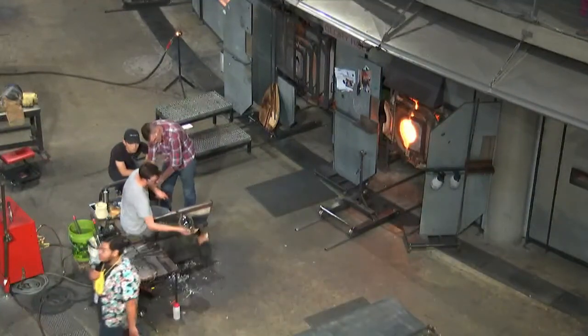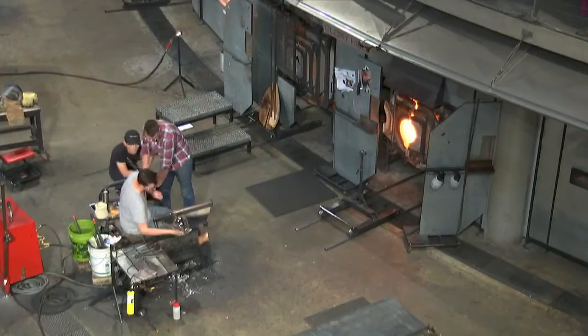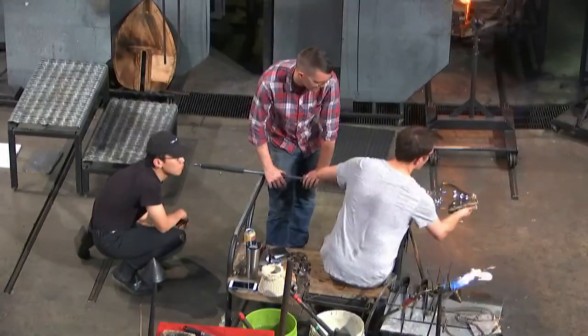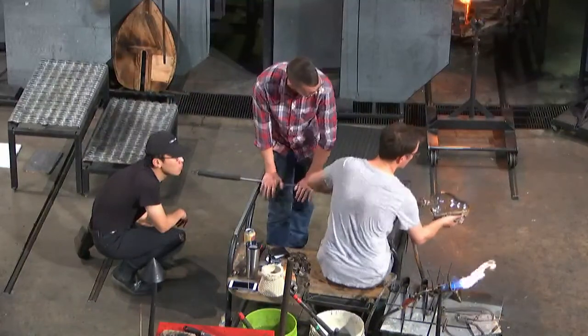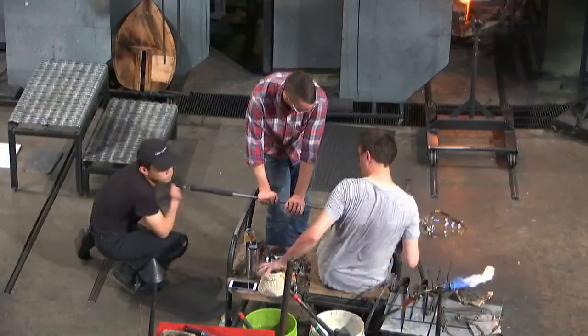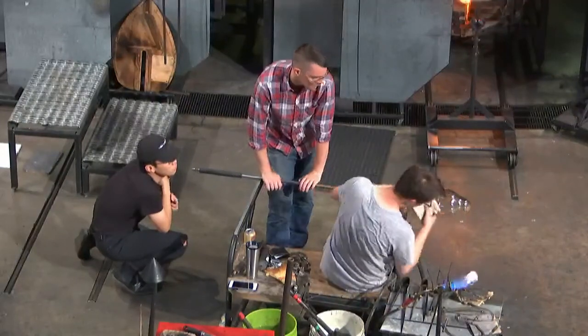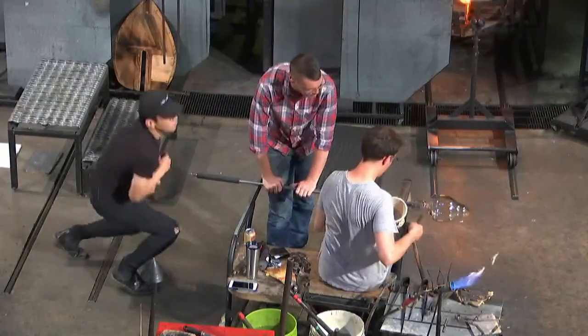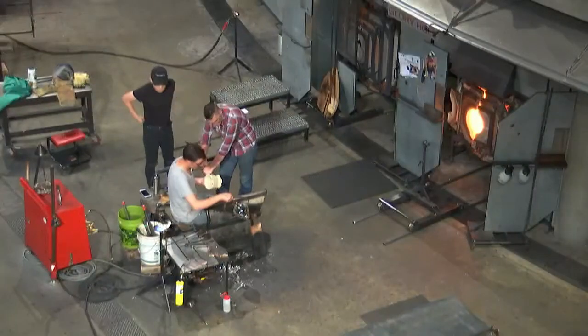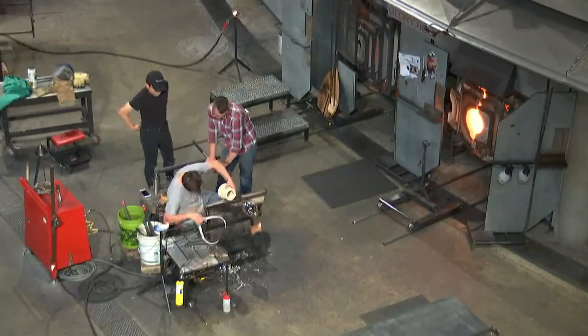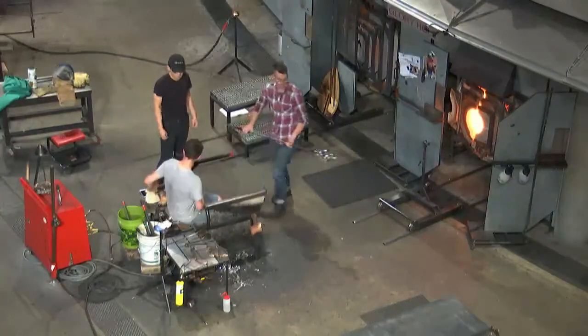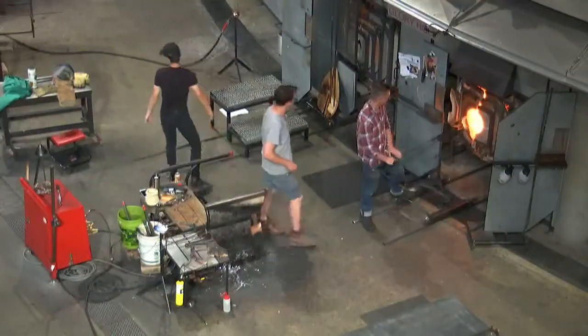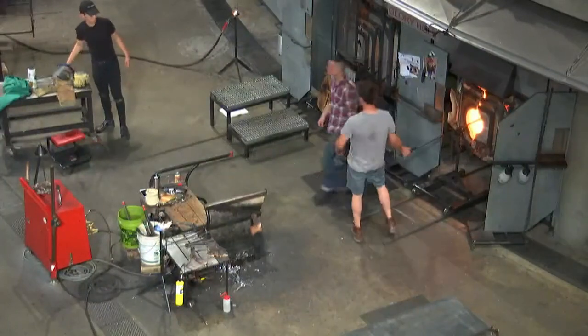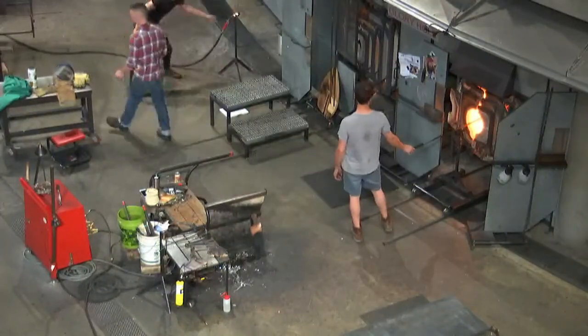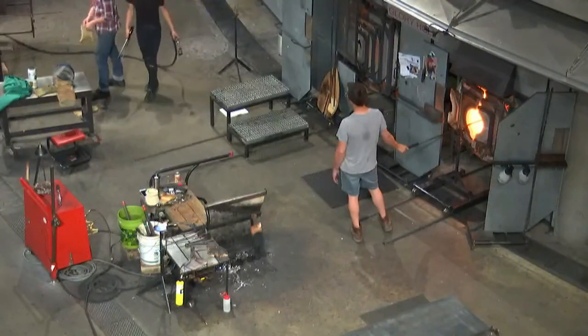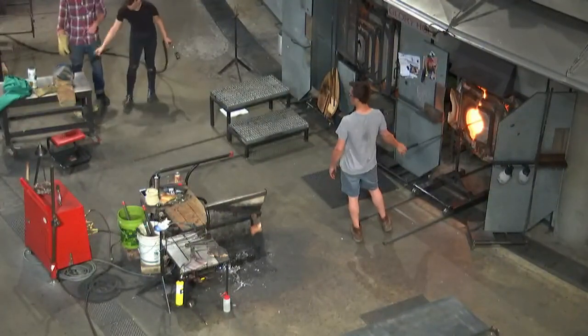As we continue this live glass making demonstration, remember that all this glass that we're working with is coming out of one of our two furnaces. We are melting 1,000 pounds of glass in each furnace, and we have two of them. They're always turned on about 2,100 degrees, about the same temperature as molten lava. We then are entering these glory holes to continue to soften the glass and make our working time longer. As the glass stays outside, it's chilling, it's getting colder, and you can no longer manipulate it to a certain point. So if we want to continue the glass making demonstration, we will have to reheat the glass to ensure that it won't break or crack.